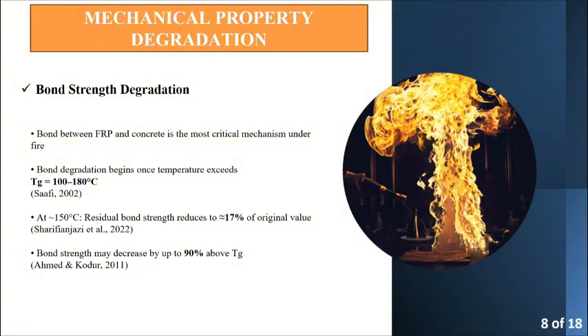Research also showed that at a temperature around 150 degrees Celsius, the residual bond strength can drop to about 17% of its original value. And in some cases, the bond strength can decrease by up to 90% when the temperature exceeds Tg, as Ahmed and Kodur have shown in their studies. So very often, bond failure happens before complete material failure. That means that the structure may fail because the reinforcement and concrete stop working together, even if the fibers are not completely damaged.